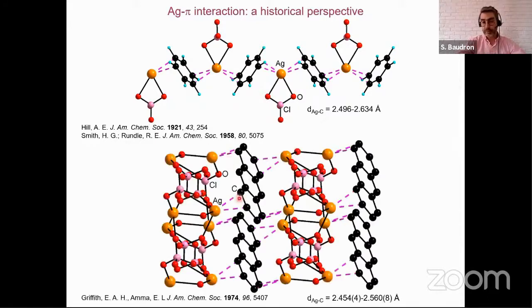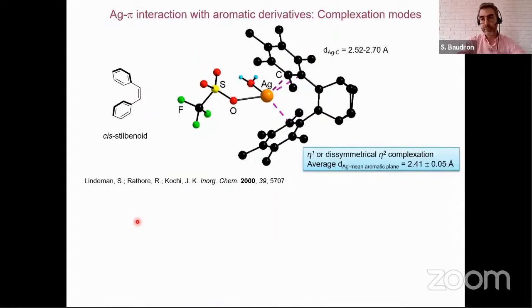We can here show the assembly of an anthracene with silver perchlorate once again, where you see a rather complex network of silver-pi interaction and coordination of a perchlorate anion. So the group of Kochi went into trying to determine the geometrical parameters of this interaction by studying a series of cis-stilbenoid derivatives and their assembly with silver cation. What they've shown with those systems is that the silver cation is interacting with a carbon-carbon bond, either in an eta-1 or a dissymmetrical eta-2 complexation, with a distance to the average plane of about 2.4 angstroms.